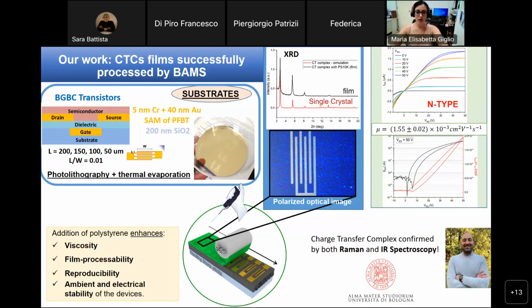So about the fabrication, well, we do several things, because we start from zero basically. So we fabricate bottom gate, bottom contact transistors. What we do is photolithography in order to expose the silicon wafer to the pattern that we want. And then the technician performs thermal evaporation of the electrodes, which are basically 5 nanometers of chromium and 40 nanometers of gold. And then we activate the gold by oxygen plasma, and deposit a self-assembled monolayer of PFBT on the electrodes in order to better align the work function of the gold with the work function of the material.